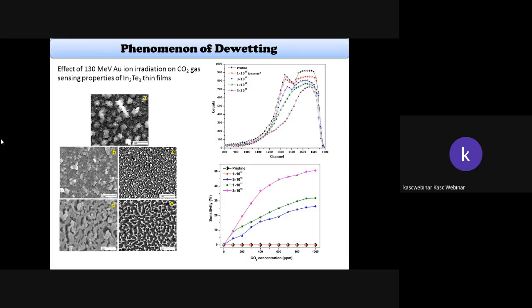And the second graphical diagram indicates the RBS, or Rutherford backscattering spectra, of the irradiated sample. The first black one indicates two different peaks, especially in the region of channels from 1300 to 1700, indicating the bilayer nature of the sample. But after irradiation with 3 into 10 to the power of 13 ions per centimeter squared, the violet line indicates the formation of a single compound. So clearly we can confirm that after irradiation there is no individual layer system. It gets mixed, so we can say that the system is a very miscible one.